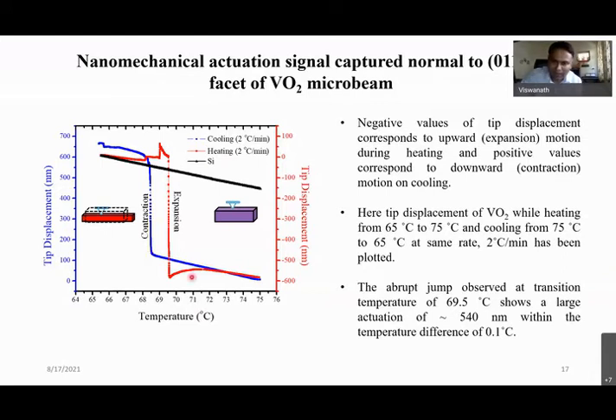But what we did is we tried with different rates. When we do a very quick heating or especially cooling, then the tip essentially gets disengaged. When you do it slowly, since we are applying a 25 micronewton load, that is able to follow it to the maximum extent possible. In expansion, you are correct, the contact is definitely intact, but during the contraction, there is a chance of more errors.